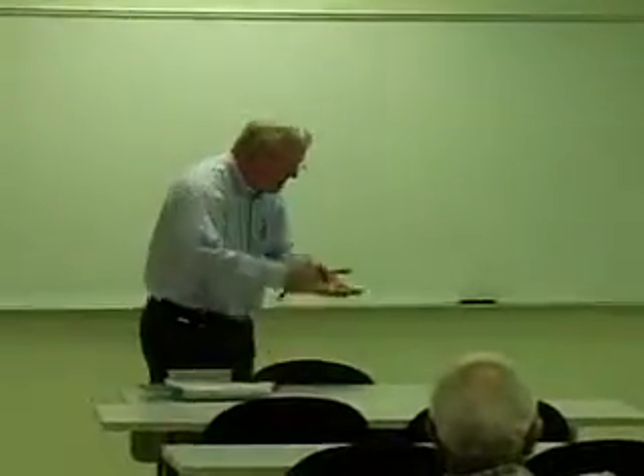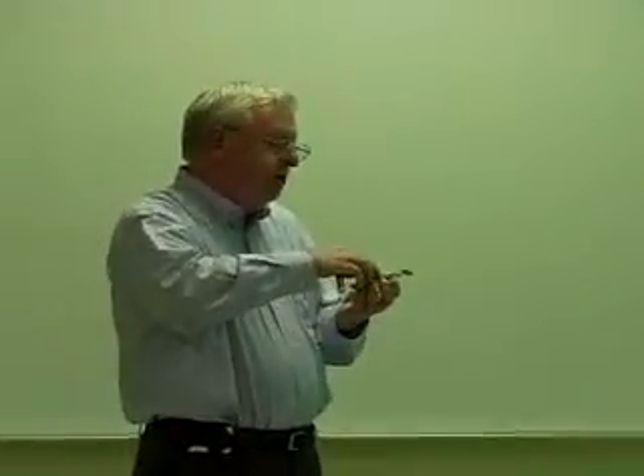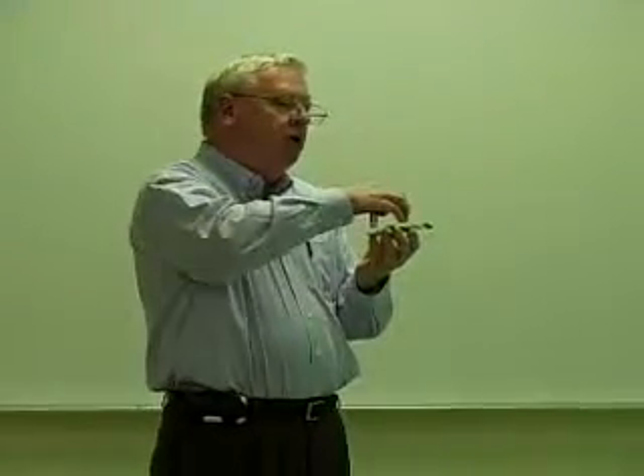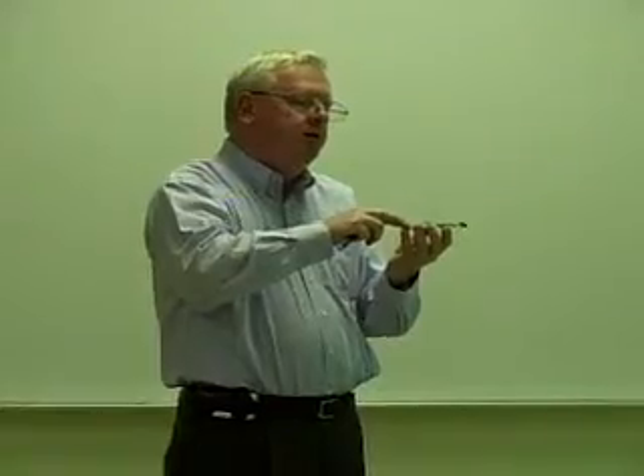Don, is wetting the lead or the solder? Yeah, if I have a pad, and I want solder to cover this entire pad, and there's a component that's adjacent to it, then what I want is for the solder to cover all of that pad. Now, if the pad isn't clean, it may retard. But I want wetting. In other words, I want the intermetallics to start forming over this entire pad as I cool it. So yeah. And sometimes with lead-free, you don't get that.